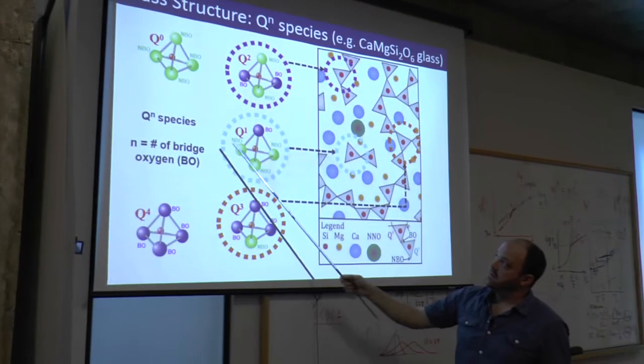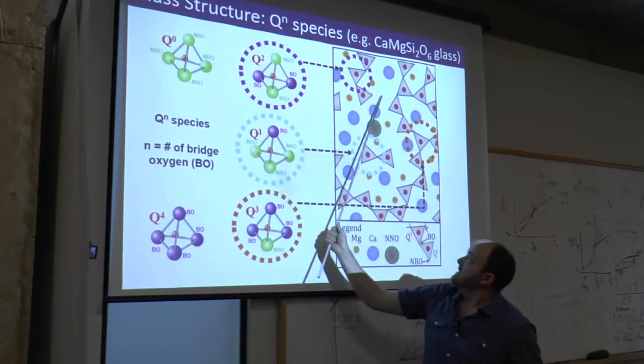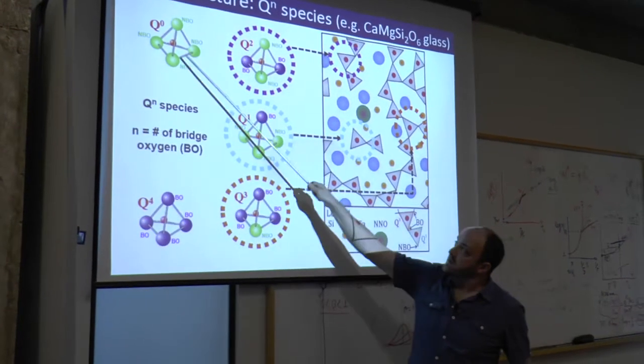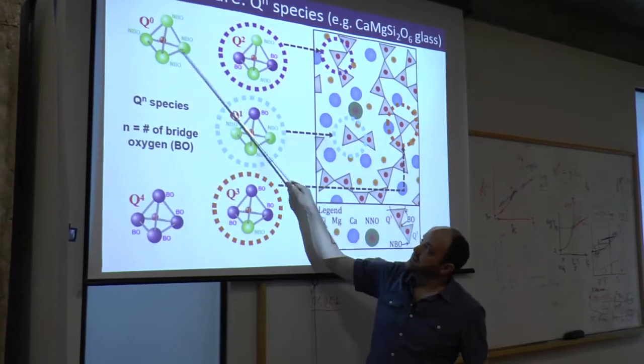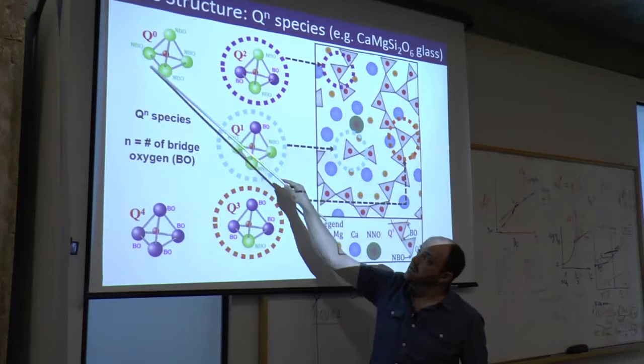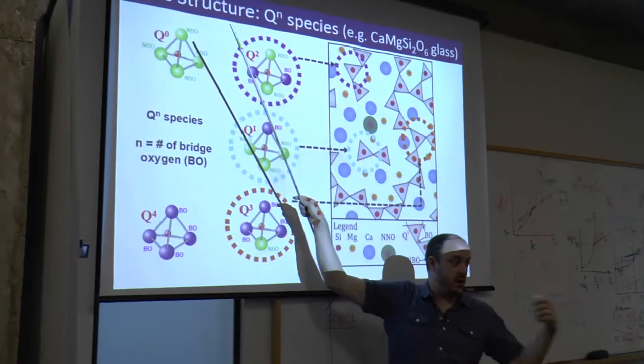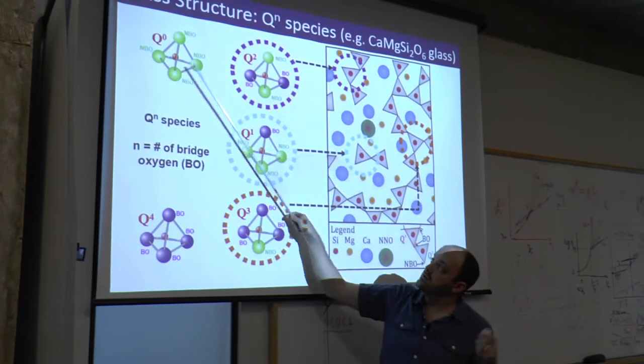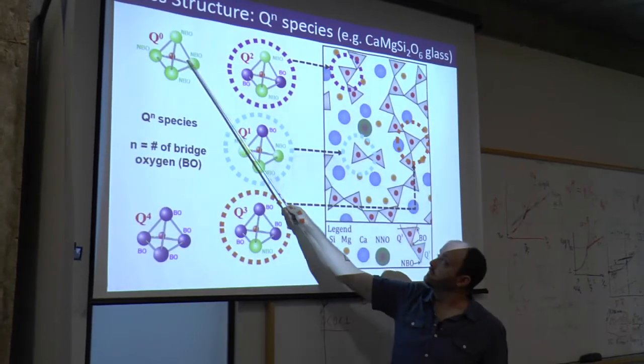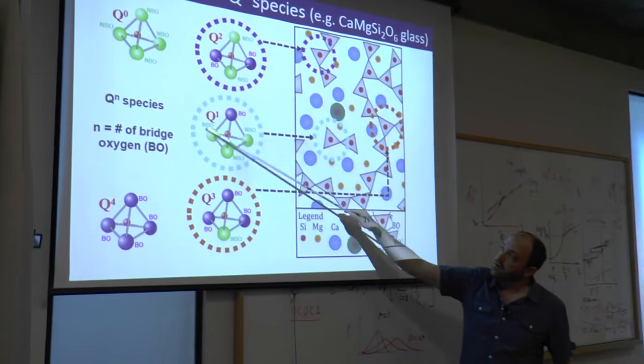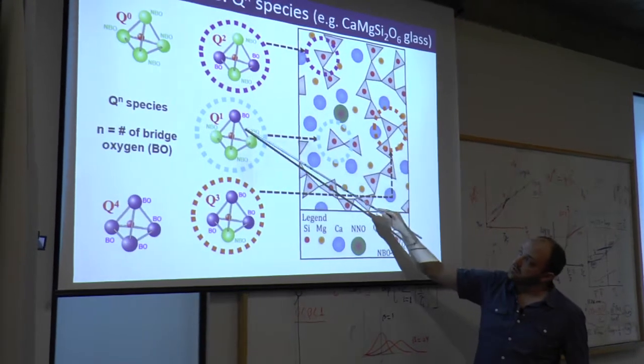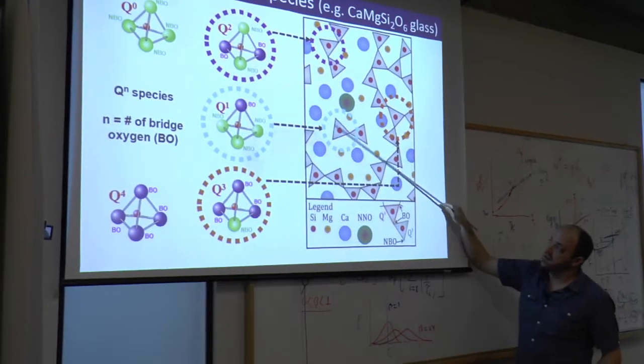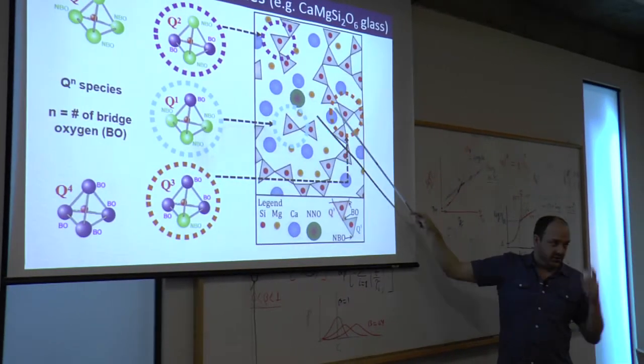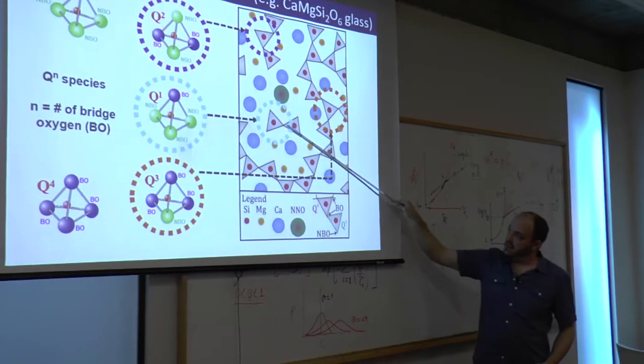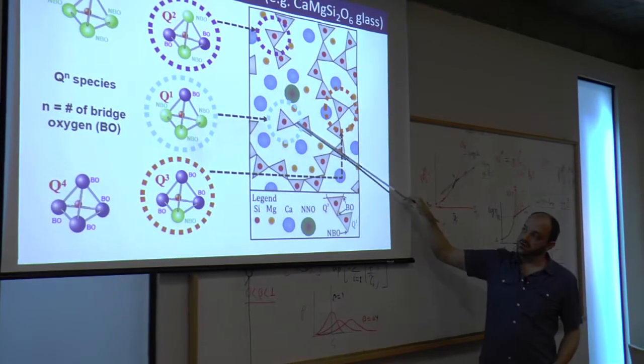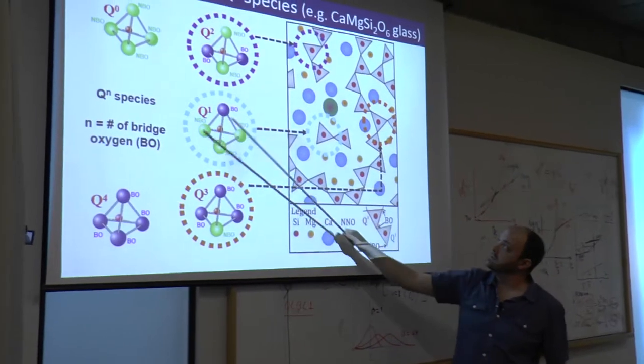So what do we mean by the QN species? In this glass, there are no Q0s or Q4s. A Q0 is a silica tetrahedron with 4 oxygens surrounding it, and they are only bound to network modifiers. There's no bridge to another tetrahedron. If we go up one to a Q1 species, this is a tetrahedron with 1 bridging oxygen. Here's an example, remembering that this is in 2D, not 3D, but this is bound only to 1 other tetrahedron. So this is what we call a Q1 species.